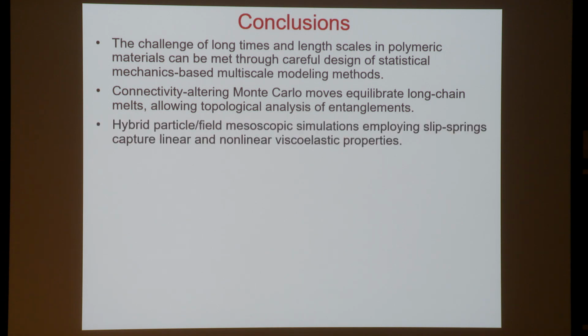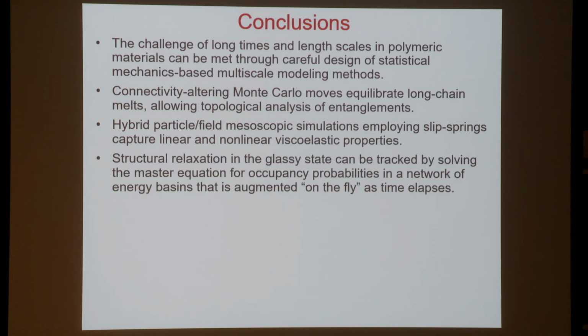Now, based on this kind of information, one can design hybrid particle field mesoscopic simulations which employ slip springs to represent the entanglements. These are by roughly 3 orders of magnitude faster than molecular dynamics, and one can try to capture the linear and nonlinear viscoelastic properties of melts. In the glassy state, one can calculate volumetric properties, elastic constants, even plasticity that I did not show, but the challenge is to calculate the structural relaxation that a real-life glass would exhibit as a function of time.